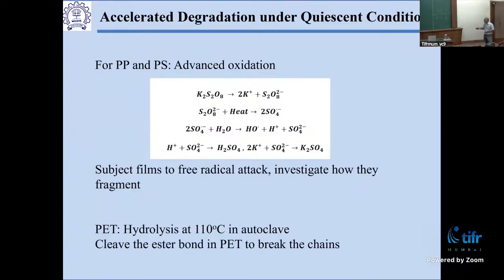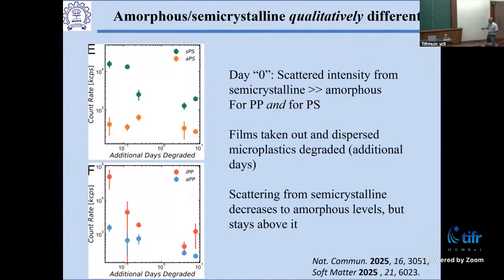With PET, we adopted a different method. This is an ester, so I can simply hydrolyze it. So you take it in an autoclave at 110 Celsius and you just sort of cook it until it falls apart. But I'm going to show you results on polypropylene and polystyrene, which is using this particular chemistry. The results are qualitatively similar to what we see with PET. Okay, so first thing, right?